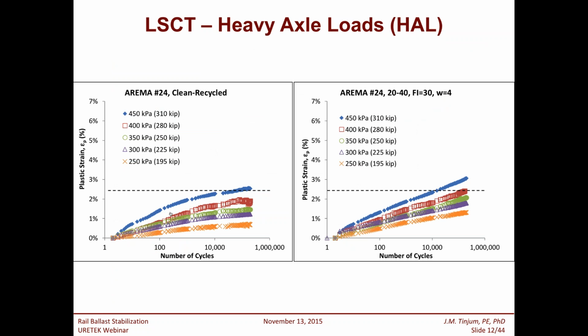So I'm going to give you some results here for about the next 10 minutes, and then in the final 10-15 minutes of the seminar, I'd like to talk about the polyurethane stabilized ballast to address these deficiencies that you're going to see in these upcoming slides. So first, heavy axle loads is what you see in the graphs in front of you. These are actual research results showing that the heavier the load of the car, the more plastic strain accumulation occurs. So it makes sense, but the degree of increase is quite interesting.